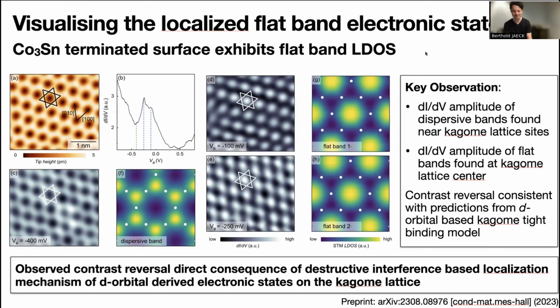Wow, that's a theorist question. Sorry, this is a very good question. Of course, these are the signatures one strives to find. But let me say it bluntly: no. The reason is that this is a very complex system. I'm showing you these beautiful pictures, which all make sense when we look at this very simple toy model. The details are described in the preprint, you have to wait for this. It's basically a simple Kagome tight-binding model that assumes a spinless system with all the d orbitals per lattice site, and then makes STM simulations based on the calculated eigenstates using a realistic atomic ion radius of cobalt. So there's no magic involved, and you can already reproduce our observations.